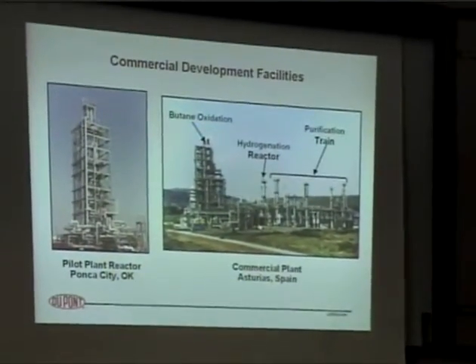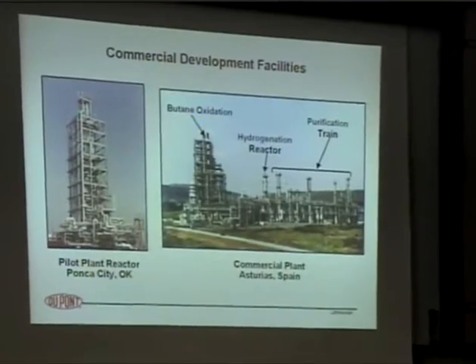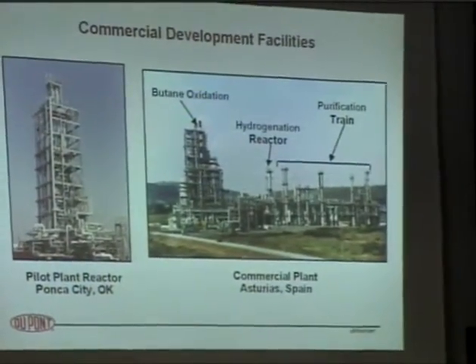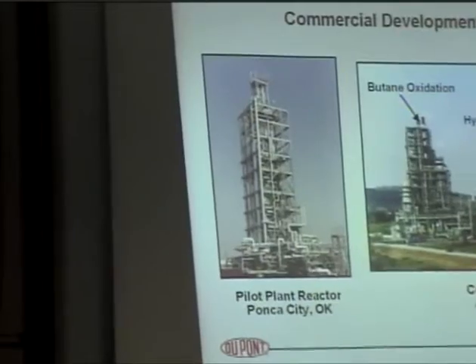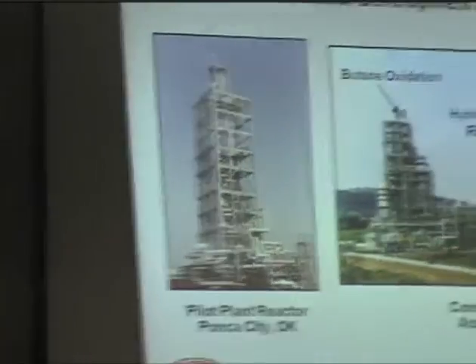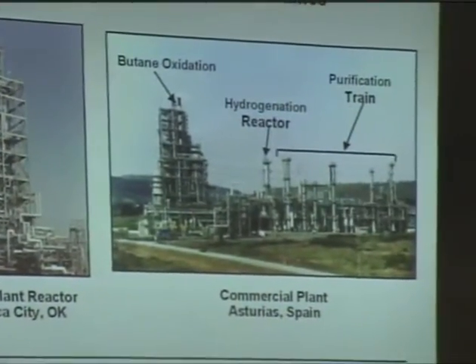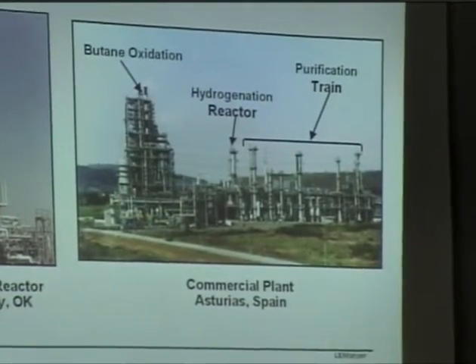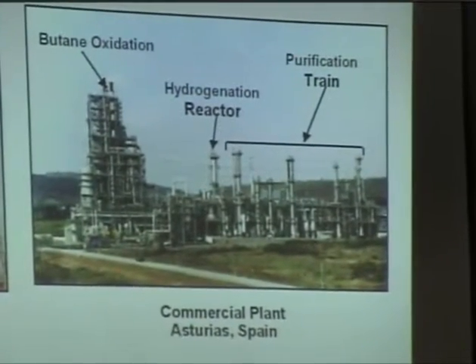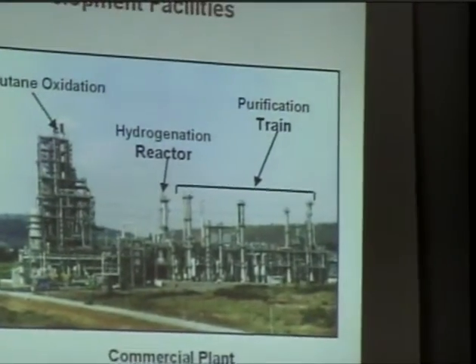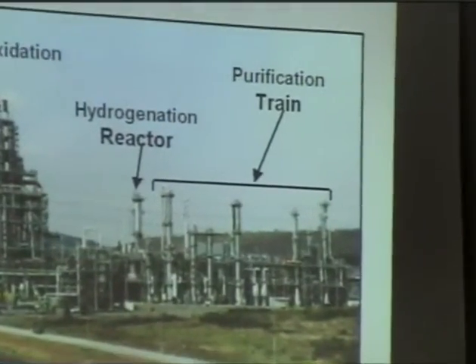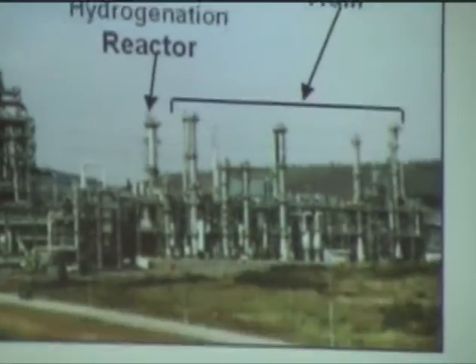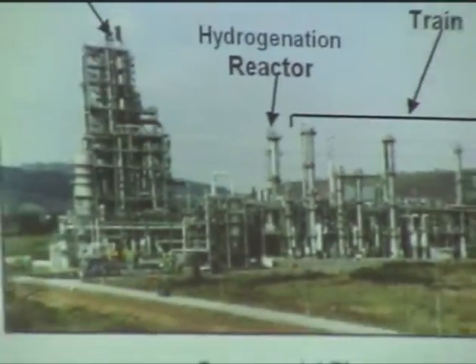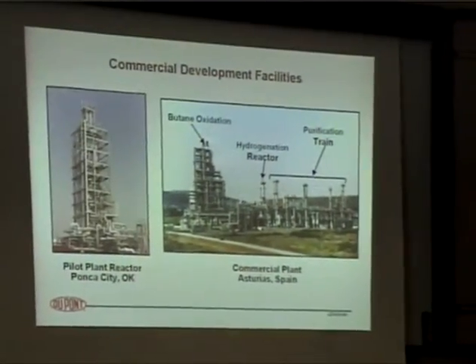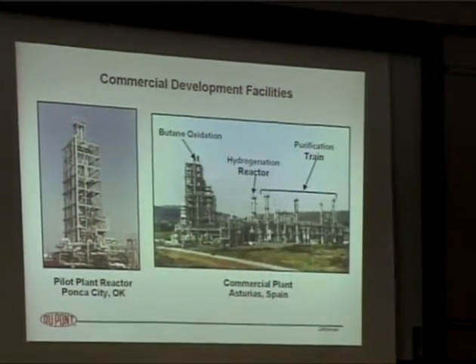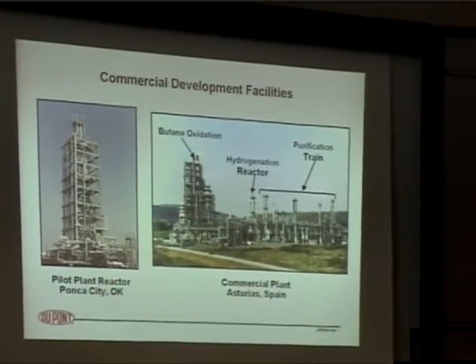One of the biggest issues we faced very early on in this process was to understand the hydrodynamics in this riser reactor. We've got all these heat exchangers in there. Was the catalyst going to be attrition resistant? What kind of performance were we going to get? So we actually built this full-scale riser reactor at Ponca City, Oklahoma, our Conoco facility at the time when we owned them. And we used this riser. It was about a foot and a half to 2 feet in diameter. And it operated for a period of time, and it demonstrated that this process would work as expected.